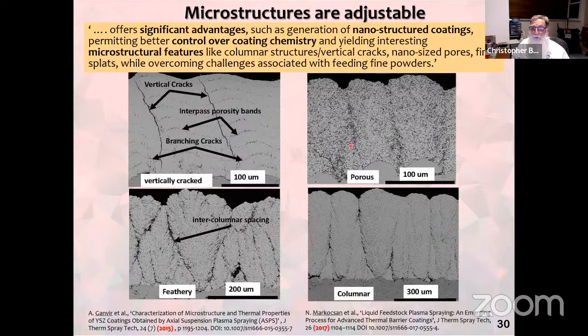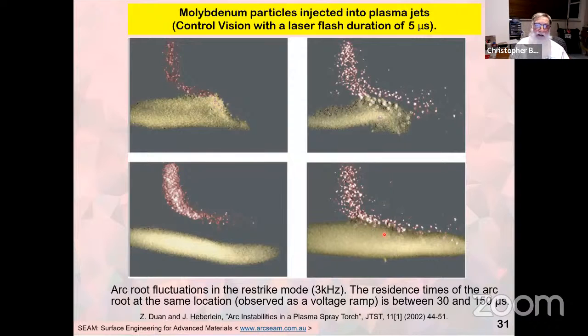And then we've got porosity of various density. I can actually see a band here. This has not been quantified with regards to whether the distribution is even or not, but it's there. And then you've got the intercolumnar spacing, feathery, and columnar. This is a liquid thermal sprayed coating. Extremely interesting because it's been produced under ambient conditions. So let me remind you as I go into the last few slides.